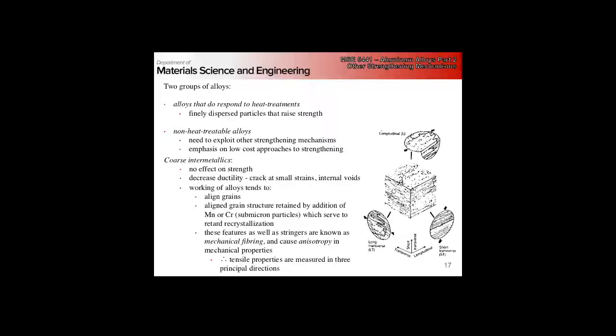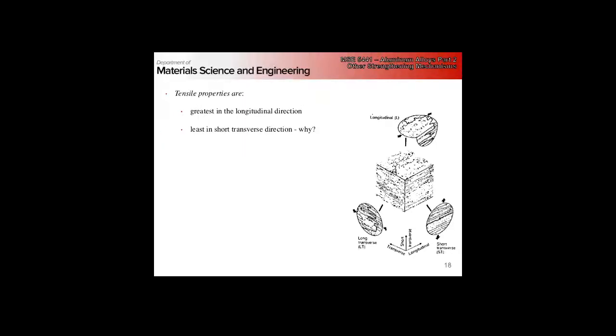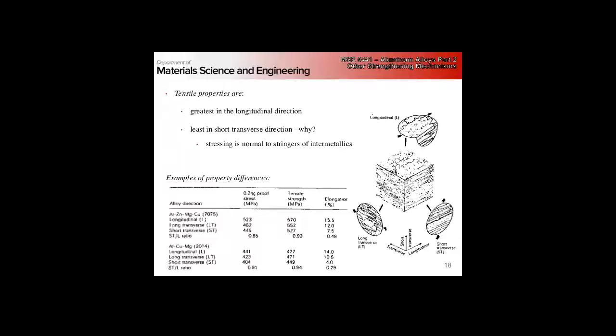So if we think about rolling, along the fiber length is the rolling direction, because we're taking these grains and smashing them out. So these aren't necessarily just stringers; these are sort of plate-like regions where you have a whole bunch of particles embedded. So it makes sense if we think about pulling along the rolling direction, pulling transverse to the rolling direction, and pulling along the normal direction. The normal direction is what is called short transverse here. Our properties tend to be the greatest in the longitudinal direction and least in the short transverse, due to the fact that we're now pulling in an orthogonal direction to these stringers of intermetallics.